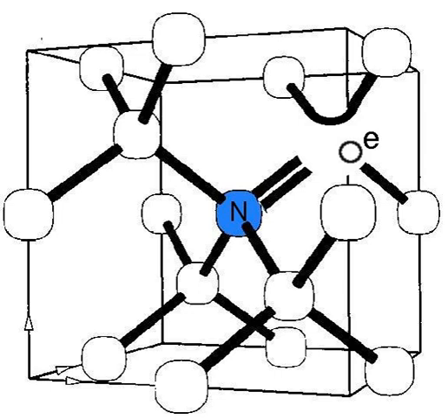It used 532 nanometer pumped NV- centers held within a high Purcell factor microwave cavity and an external magnetic field of 4300 G. Continuous maser oscillation generated a coherent signal at approximately 9.2 GHz. The NV center can have a very long spin coherence time approaching the second regime. This is advantageous for applications in quantum sensing and quantum communication. Disadvantageous for these applications is the long radiative lifetime, approximately 12 nanoseconds, of the NV center and the strong phonon sideband in its emission spectrum. Both issues can be addressed by putting the NV center in an optical cavity.